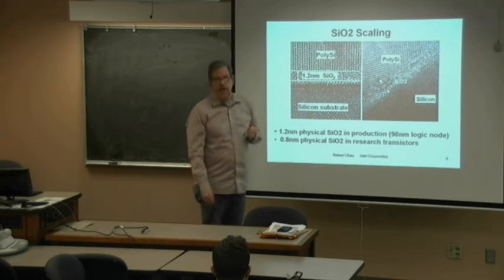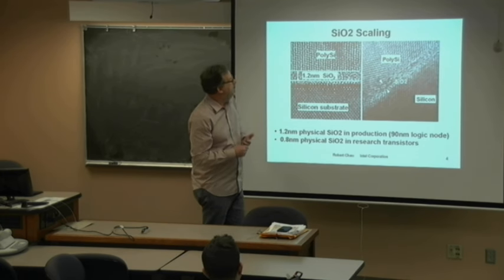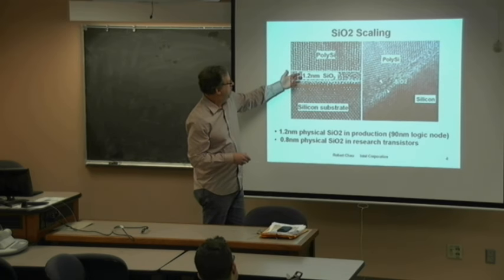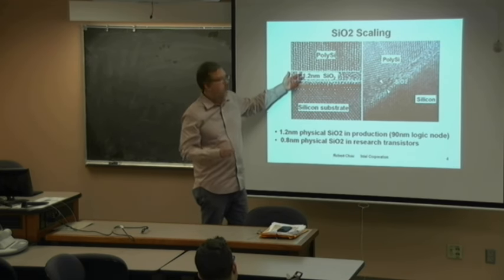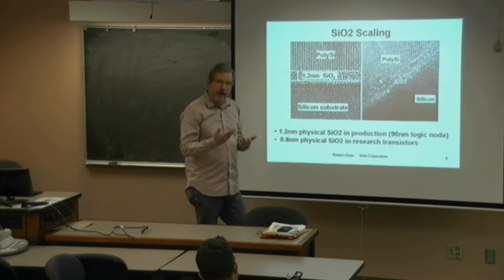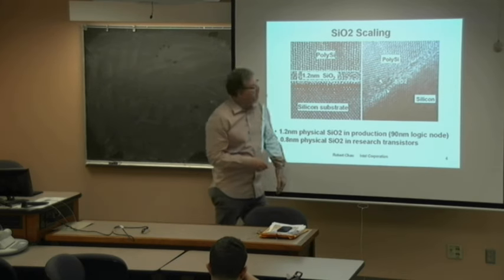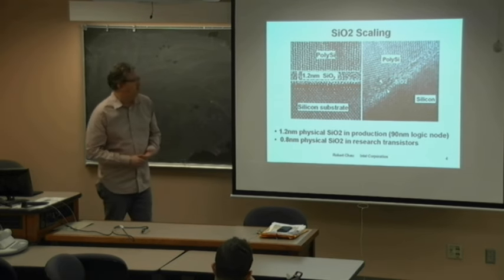This is one of the things, and this is related to your computer problem, is the scaling of that gate dielectric. Whereas the traditional SiO2 scaled to 1.2 nanometers, and I think it got as small as 0.8 nanometers before they finally segued over to the high-K dielectric.